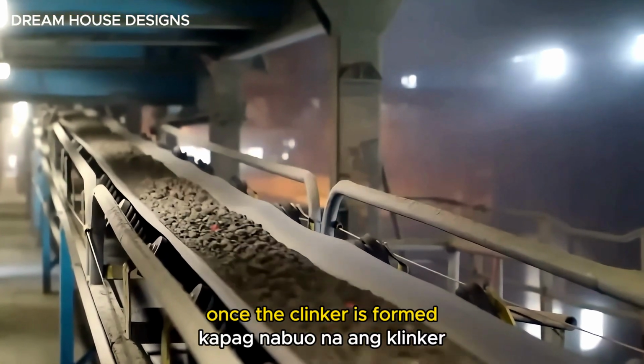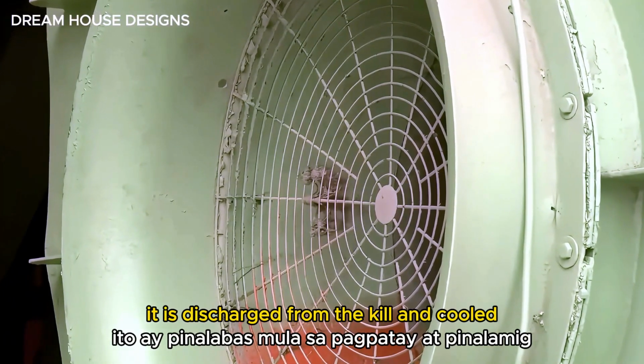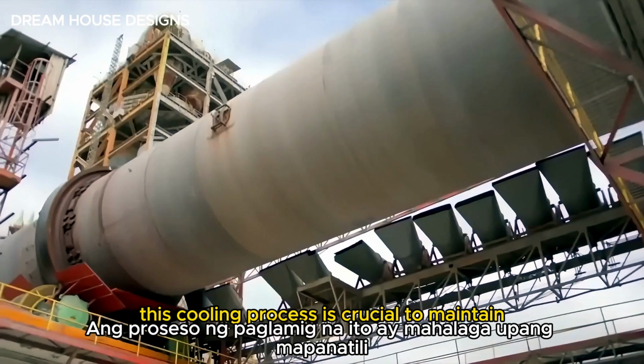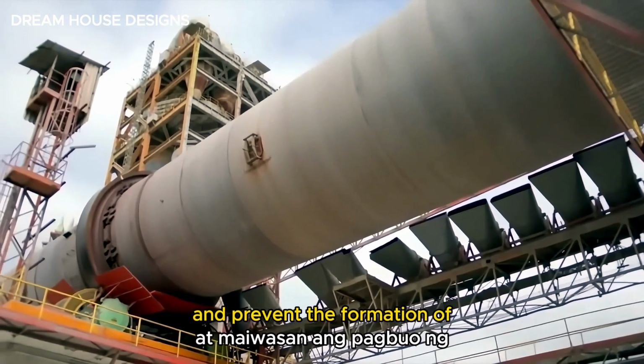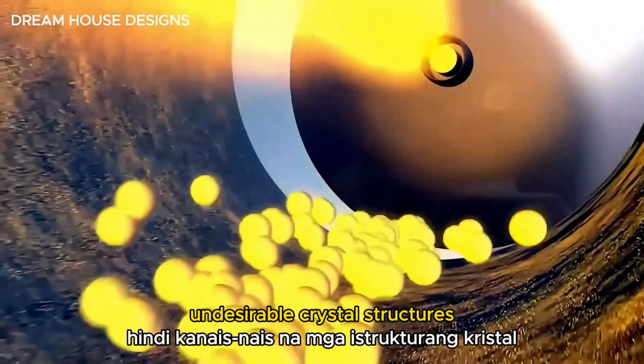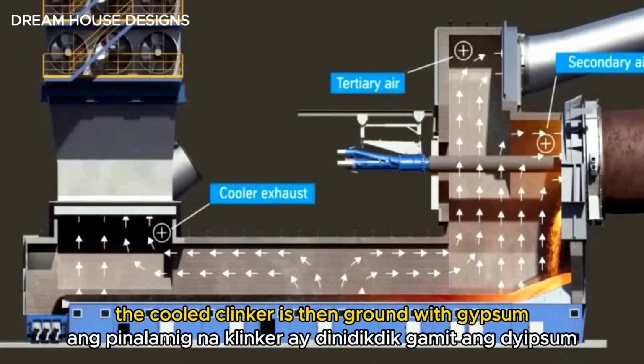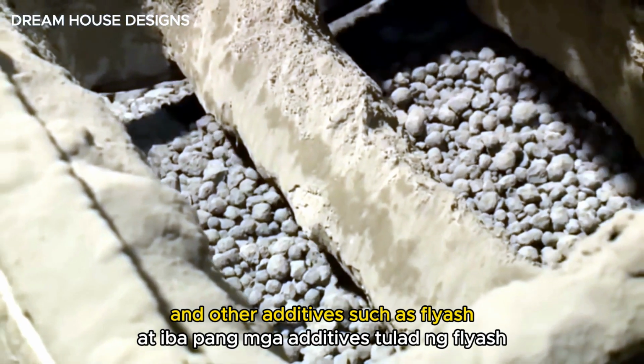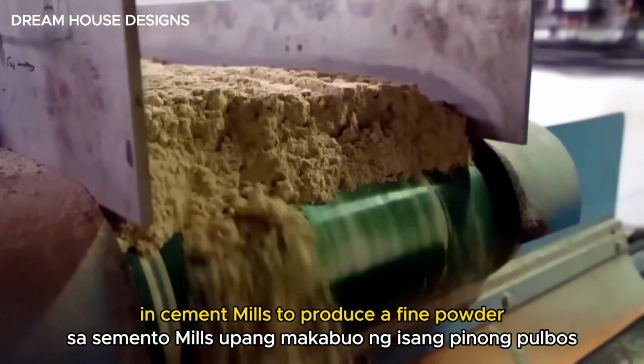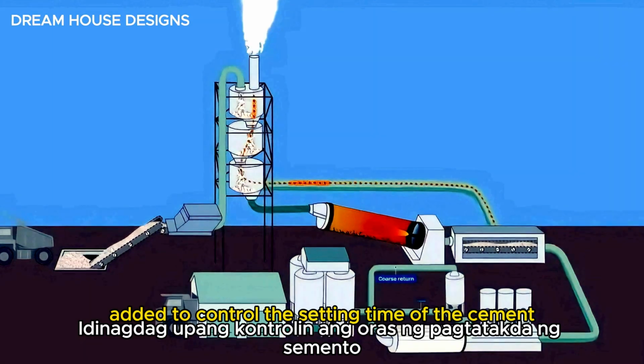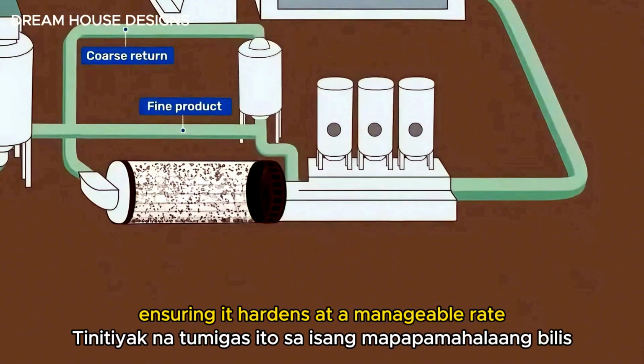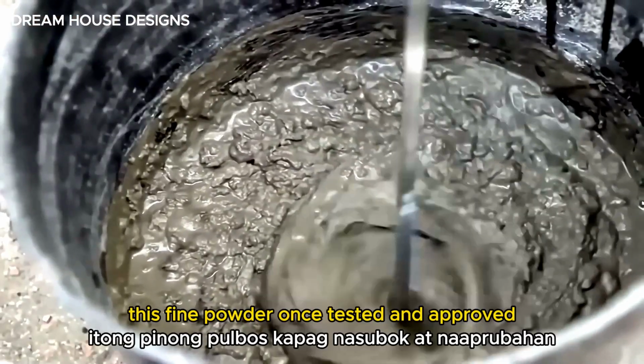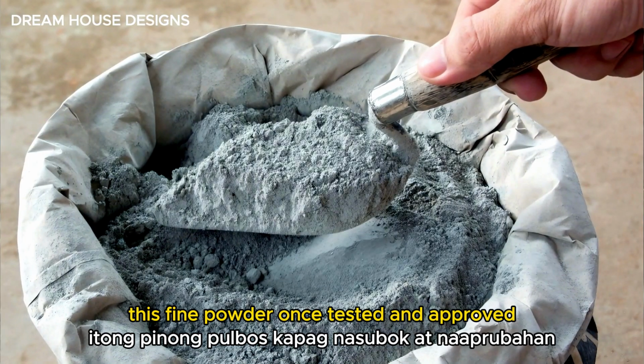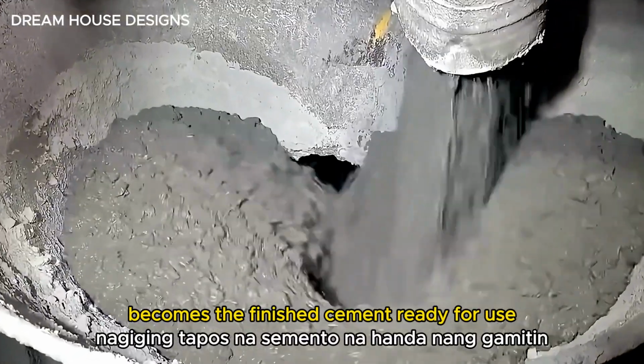Once the clinker is formed, it is discharged from the kiln and cooled using air blown through it. This cooling process is crucial to maintain the quality of the clinker and prevent the formation of undesirable crystal structures. The cooled clinker is then ground with gypsum and other additives such as fly ash, slag, or pozzolana in cement mills to produce a fine powder. Gypsum is added to control the setting time of the cement, ensuring it hardens at a manageable rate. This fine powder, once tested and approved, becomes the finished cement ready for use.